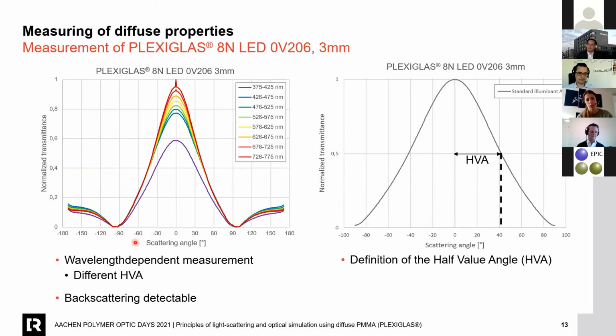First, the forward scattering from -90 to 90 degrees, and the signal is defined in wavelength packages because the dependency on wavelengths for each wavelength is not so high. And in these packages, you can see the dependence better. And you see that the red light has lower scattering properties. At 0 degrees, you have a part of unscattered light that goes through the sample without any scattering effect. And with a lower wavelength, the scattering properties get higher.